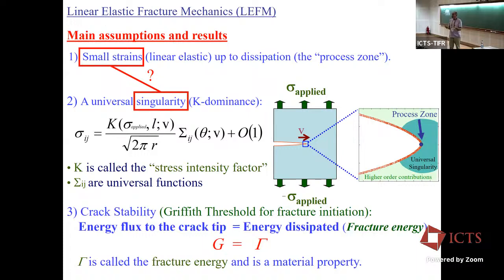So you always have small defects in the material, but this coefficient depends both on the amount of stress that you apply. So if you have a very, very small defect, you would have to apply a very, very large stress to get to some critical value, which is defined by this. I'll go into it a little bit more in detail, but this funny coefficient squared is basically the energy flux into the tip of the crack. So if this is too small, you won't be able to equate the dissipation, the amount that you need for dissipation, the crack, and a crack will exist. It will create the stress singularity, but it won't propagate. Okay, great questions. Thank you for them.